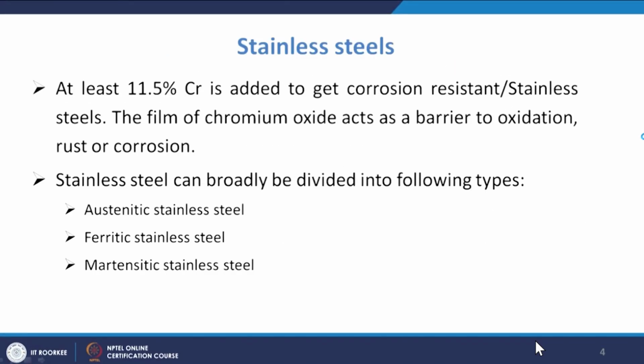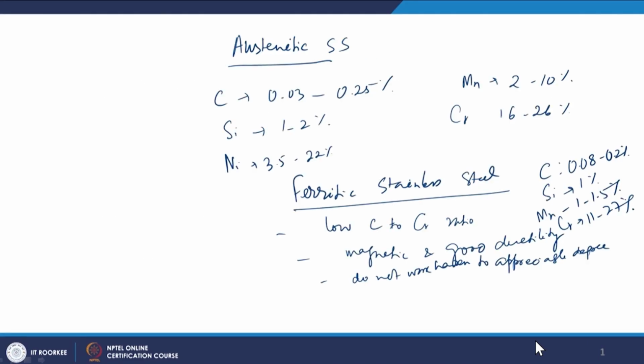Okay, so one example of this is stainless steel. At least 11.5 percent chromium is added to the steel to get good corrosion resistance. This film of chromium oxide acts as a barrier to oxidation, rust or corrosion. Stainless steels can be broadly divided into the following types: austenitic stainless steel, ferritic stainless steel, and martensitic stainless steel. In austenitic stainless steel, carbon is generally 0.03 to 0.25 percent, manganese 2 to 10 percent, chromium 16 to 26 percent, silicon 1 to 2 percent, and nickel 3.5 to 22 percent. This nickel is the austenitic phase stabilizer.